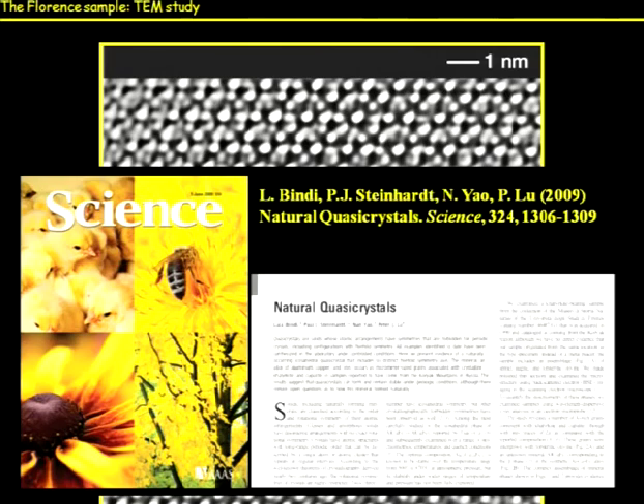Unfortunately, some months later, the situation went very bad. As Danny had to fight a lot with the physical and chemical community because of skepticism, we encountered something like this in the geological and geochemical community, because our natural quasicrystal shows metallic aluminum inside. A lot of people do not believe in the presence of metallic aluminum on the Earth, because it needs too strongly reducing conditions to form. So it is not possible to find. Even though there are a lot of occurrences reporting metallic aluminum, this would be considered an unnatural, man-made material, slag material. So we had to fight a lot to demonstrate that this is natural.